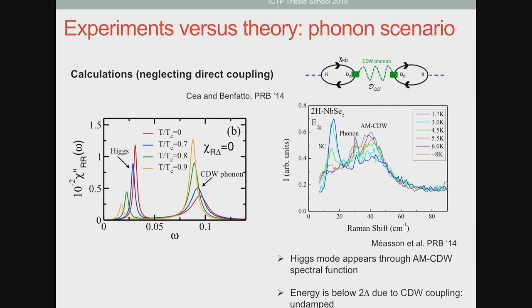So you can actually do a more microscopic calculation, not just of the phonon spectral function, but actually of the total Raman response. This was done by Cea and Benfatto. So this is really calculating these kinds of diagrams, where you have the regular electronic Raman bubble that I showed you in the first lecture, and that would couple to the CDW phonon. And this CDW phonon will in turn couple to the Higgs mode. And if you do that, what you see is that indeed, once you cross TC, there is a spectral weight transfer between the CDW phonon and the Higgs mode below TC. And this matches quite well the experiment that is observed in niobium diselenide.